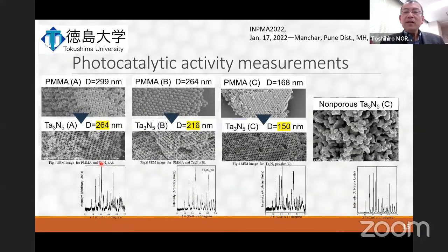This is a catalyst here. This is a PMMA template, sorry. We prepared three tantalum nitride samples with different macropore sizes, which are determined by SEM images, you can see. The largest one is 264 nanometers, the medium one was 216, and the smallest one is 150 nanometers. As a reference sample, non-porous tantalum nitride powder was also prepared here. All the samples could be assigned to the pure tantalum nitride phase, as seen in the XRD patterns.